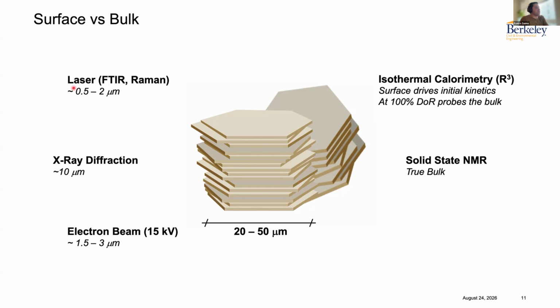So for example, laser radiation, which is what we use for Fourier transform infrared spectroscopy or Raman spectroscopy, penetrates a cementitious material 0.5 to 2 micrometers. So if I have a particle that is 20 to 50 micrometers, I'm really only sampling the surface here, and that's what brings information back to my detector. X-ray diffraction penetrates a little bit more, 10 micrometers, but still not a lot compared to the size of these particles sometimes. An electron beam in an SEM in a typical configuration for EDS, 15 kilovolts, would penetrate 1.5 to 3 micrometers. So if I have a particle that is 20 micrometers, 50 micrometers, I'm really only skimming the surface with this analysis.